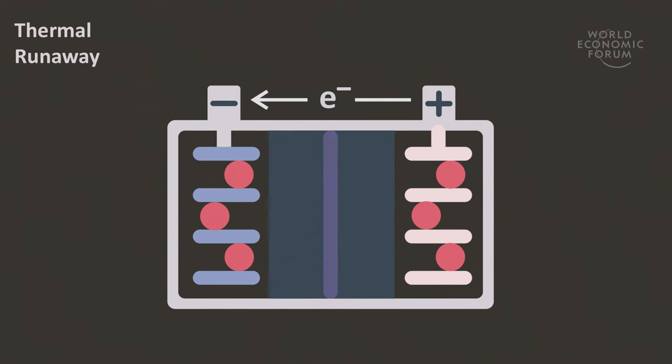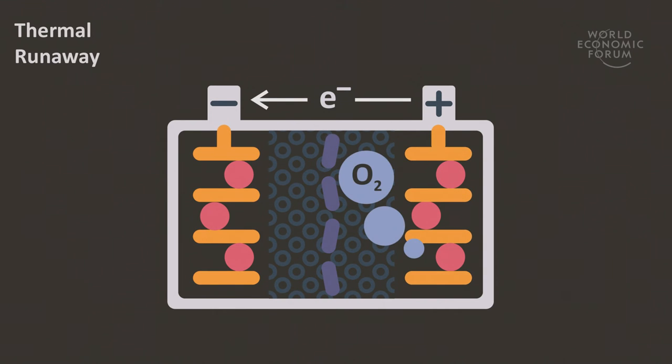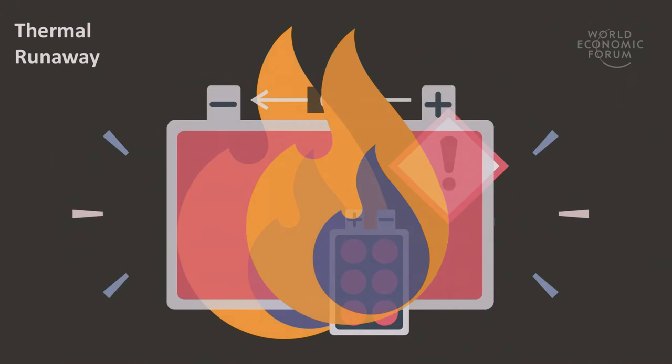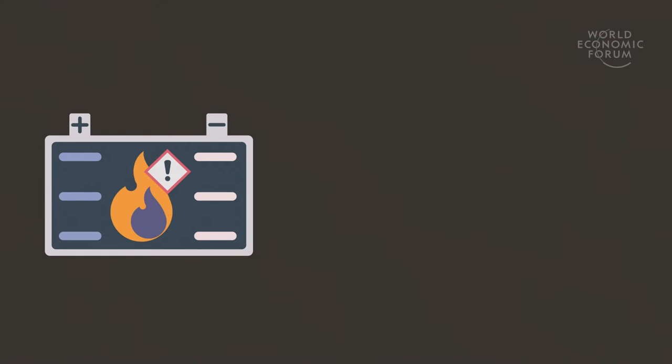Today the technology is far from perfect. It can heat up, and there's a danger of thermal runaway. During charging of the batteries, oxygen gas can be produced from the oxide electrode and react with a flammable liquid electrolyte to produce heat and cause fire. So we need to improve the safety of the batteries.